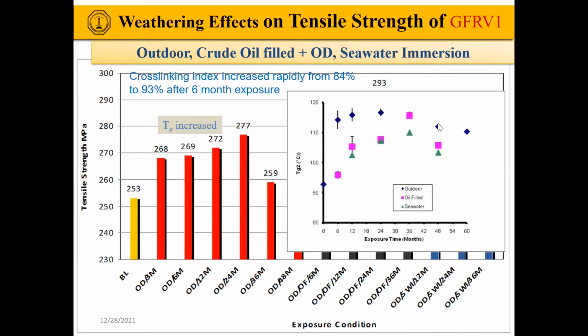As you can see here, the blue diamonds indicate the outdoor exposure without filling it with seawater. The squares indicate the oil filled, and the triangles, the seawater filled. You can see that up to about 36 months, the TG, the glass transition temperature, increases. That means that the curing was not complete when we got it. We looked at also the cross-linking index, and we have seen that it increased.